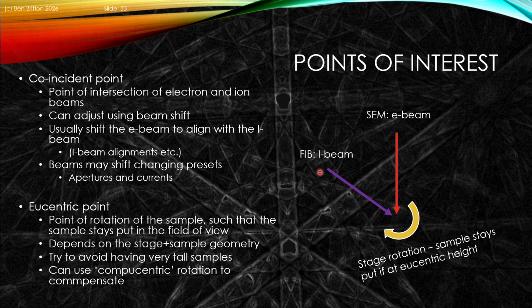in those cases. Now, as you change so-called presets, that's like apertures or other optical controls, that beam may shift. And so it's important that, if you're going to use multiple apertures in your experiment to mill with different currents or different voltages, you effectively align those presets to get the beam to be coincident between the different FIB settings that you've got.